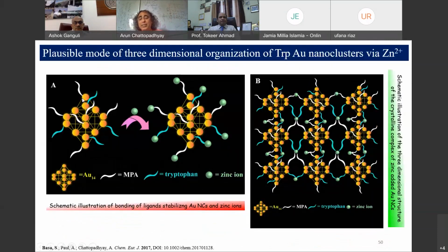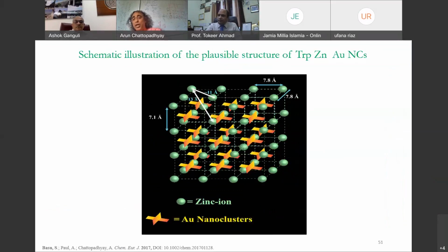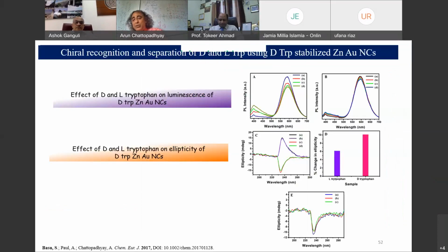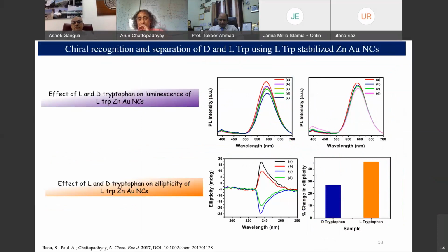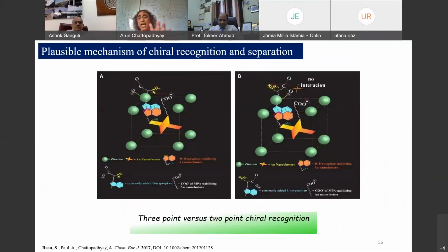We found that, depending on the ligand, these same Au14 will have different structures energetically. These will reorganize in 3 dimensions, a beautiful crystalline material. If you start with a left-handed organic molecule as the ligand, it will form one type. If you start with a right-handed organic molecule as the ligand, stabilizing the cluster, it will form another. And you can use this for 3-point interaction and not only sense enantiomers, but you can isolate them one from the other. We have shown optically many ways that I will just rush through. So this is application 2.